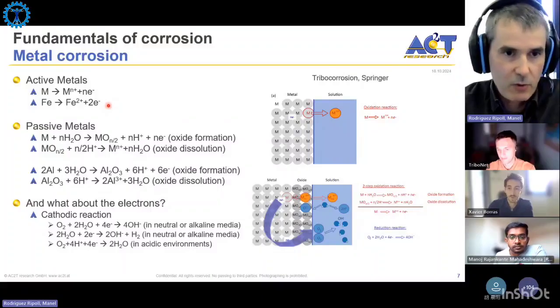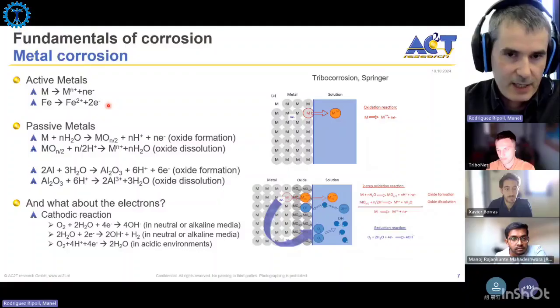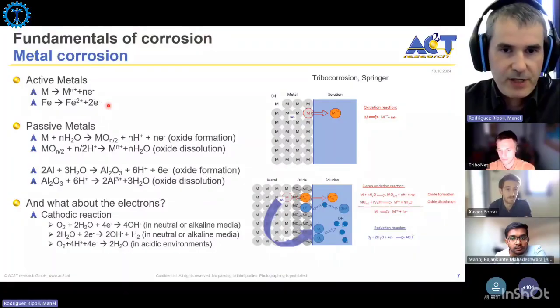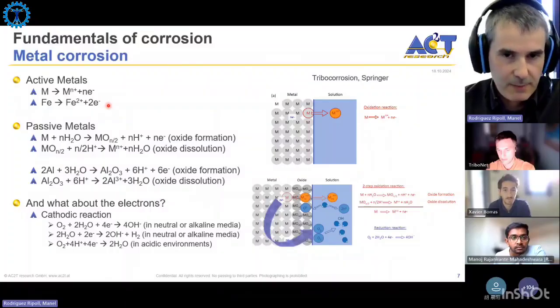It depends on what you would like to do and how stable you need it to be. For example, if you do some cathodic cleaning, so you cathodically remove the passive layer and then rebuild it again within the electrolyte, you may get more consistent results and it might be quicker. Or if you pre-treat the sample with some acid, for example nitric acid, before the experiment, you can go quicker. So it depends a bit on the system that you have.